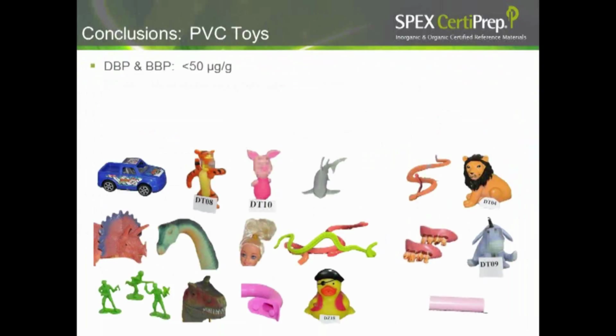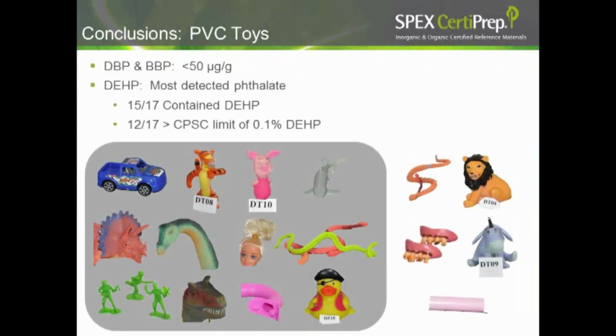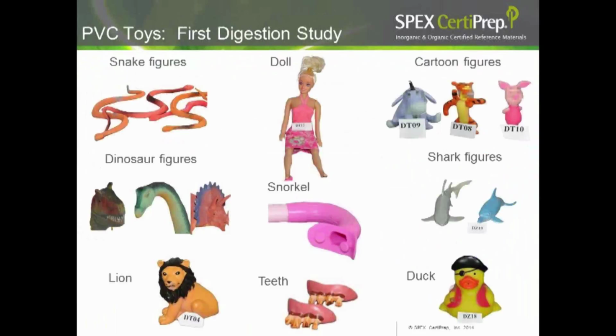So overall, what we found is several different phthalates, but DEHP was actually our most detected phthalate, and it was in 15 out of 17 of our toys. And 12 out of 17 of these PVC toys would have exceeded the CPSC limit of 0.1% and would not have been allowed to be sold here in the U.S. So we decided that these would be our first contestants in testing our metal content.